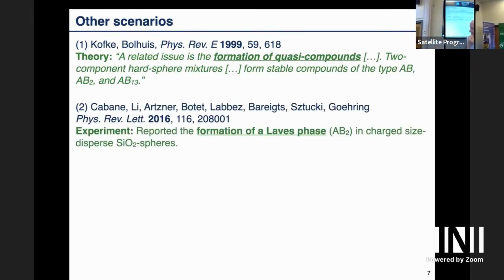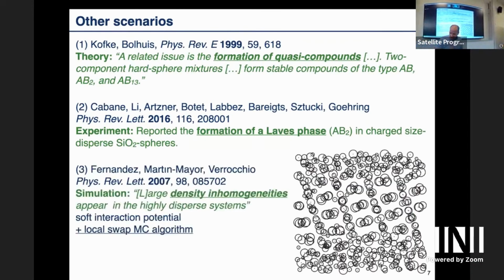Then in 2016, there were also experiments which actually found Laves phases. That's an AB2 crystal in charged size-dispersed SiO2 spheres. That's the same material as the opals. However, they're charged, and they have different charges on different particles, so at least there was some crystallization in polydispersed particles. And then there was other work. I found this work from 2007 quite interesting, which performed simulations, and they saw something like this, and they didn't really know what to make of it, and they called this density inhomogeneity.